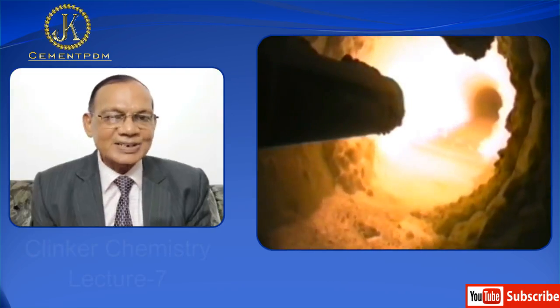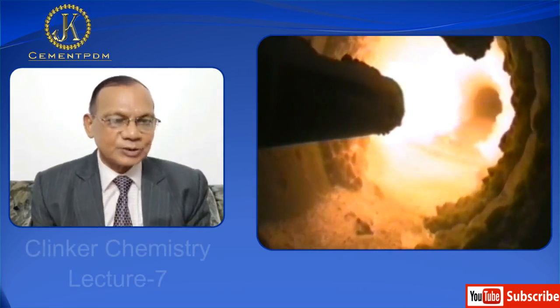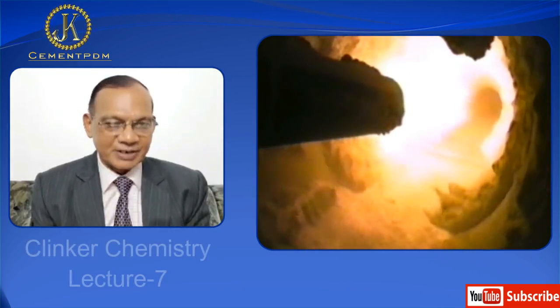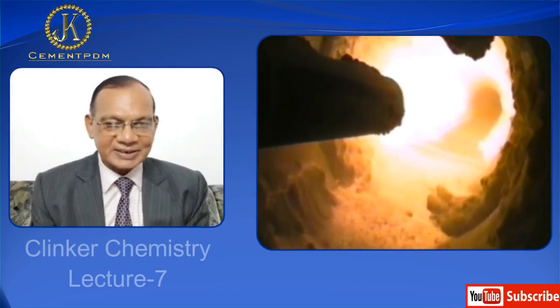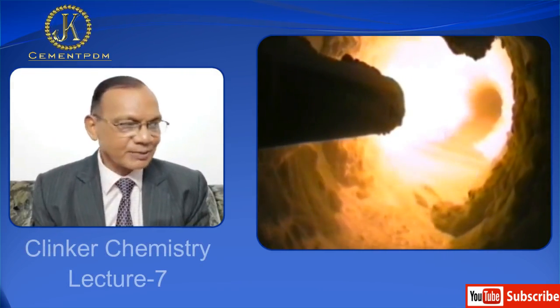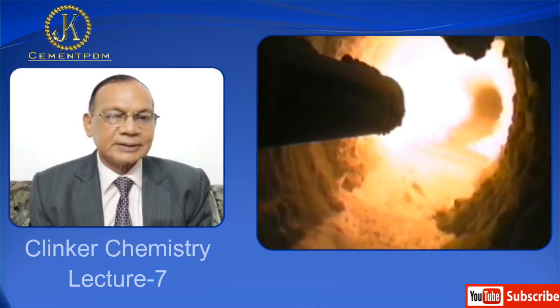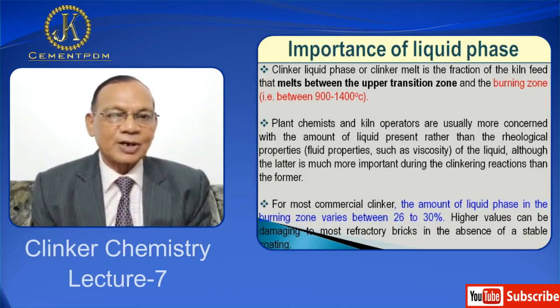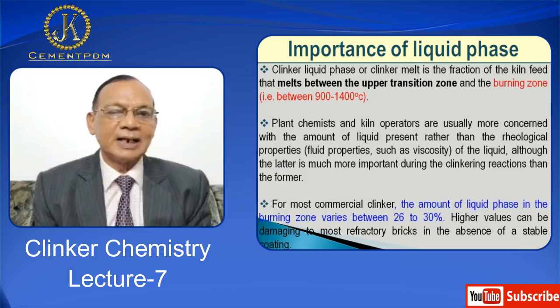So you have asked me now to talk about the importance of liquid phase. So I will discuss that in detail because this is a very important aspect. Clinker liquid phase or clinker melt is the fraction of the kiln feed that melts between the upper transition zone and the burning zone, that is between 900 to 1400 degrees centigrade.